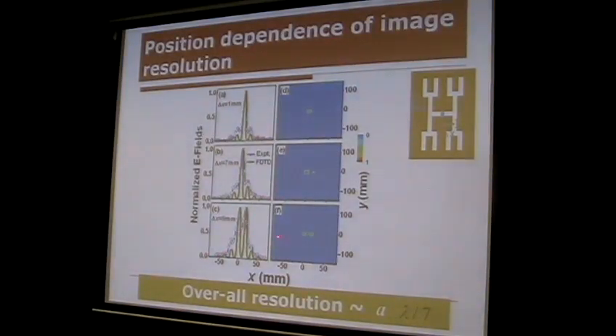Only in the situation where the source is set at the boundary between two unit cells, we found that it cannot be distinguished. It's split into two equally bright images. So by considering all this, we found that the overall resolution is actually bounded by the periodicity of the whole structure. For this structure, it's still sub-wavelength, and we calculate that the overall resolution is roughly lambda over 7, which is still sub-wavelength.